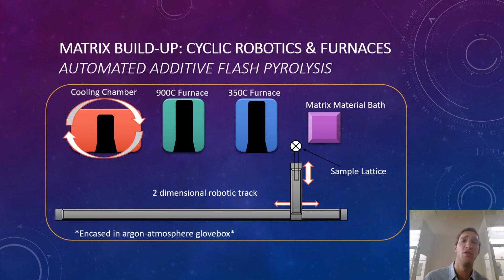First into the 350 C furnace. This is the cross-linking furnace. From the cross-linking furnace, we then move into the 900 C furnace. This is the pyrolysis furnace, and then we move into the cooling chamber. It's very important to have this cooling chamber, for if we do not have it, the precursor is too hot, so that when the polymer is redeposited onto the structure that we're looking to fill up, it doesn't wet out enough and you actually get bubbles.